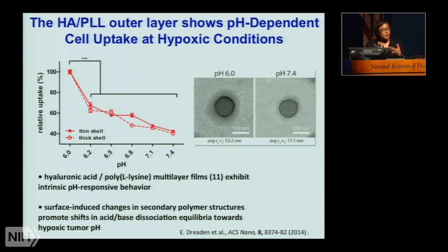Because what's happening is we're beginning to protonate those carboxylic acid groups. And as we do that, we're beginning to erase the negative charge. The net impact of that is twofold. One of them is that if you erase the negative charge, you're erasing some of the electrostatic interactions, and the film's cross-linking decreases and it begins to swell. Now, rather than this compact, negatively charged halo, we have this big, fat, but rather soft, swollen layer around the nanoparticle. The second thing that changes is the net charge.